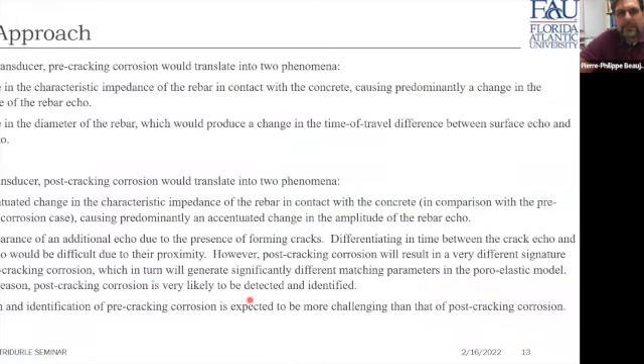Now, regarding this approach, using this transducer, pre-cracking corrosion would translate into two phenomena: a change in the characteristic impedance of the rebar in contact with the concrete, causing predominantly a change in the amplitude of the rebar echo, and a change in the diameter of the rebar, which would produce a change in the time of travel difference between the surface echo and rebar echo.